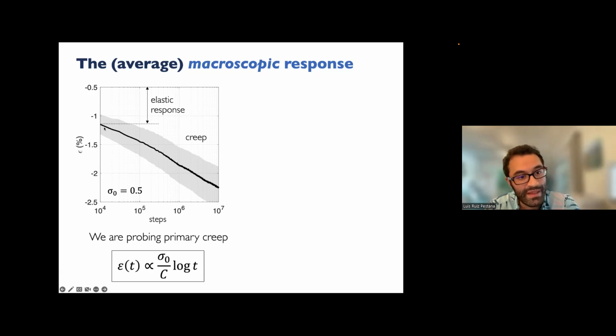So the thick black line that you see here, that's the average response over all the configurations and over all the runs. Okay. And the shaded black area that you see is one standard deviation in the response. So what you see is a quick elastic response. Okay. And then logarithmic creep. Now, this is almost textbook logarithmic creep. So what we are probing and all the statements that we are going to make from now on are about primary creep. Okay, we don't have access to secondary creep. This is what we can get with simulations. But whatever we find should be applicable broadly to primary creep, where again, the strain depends logarithmically on time.